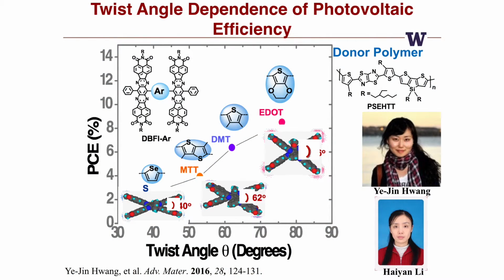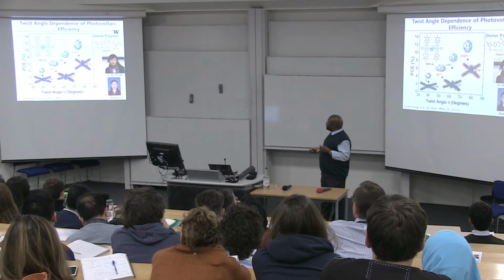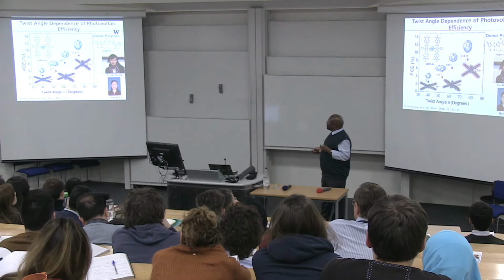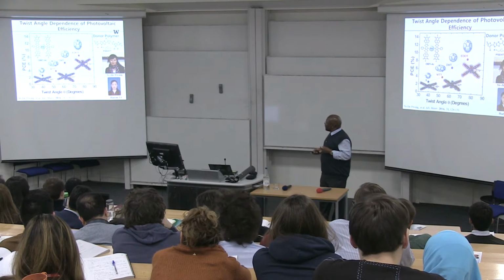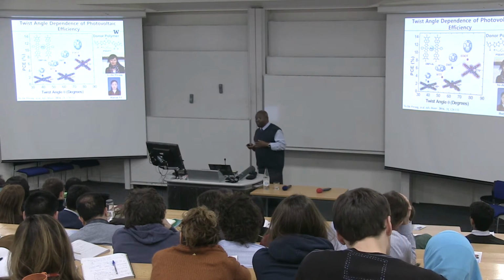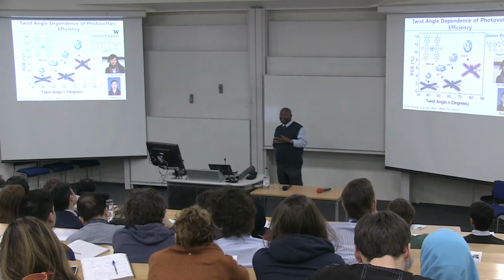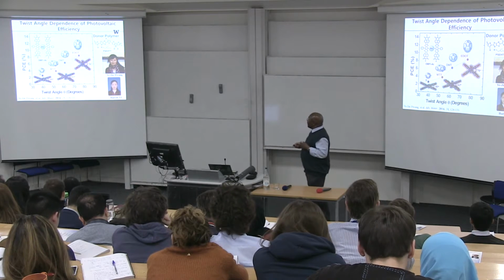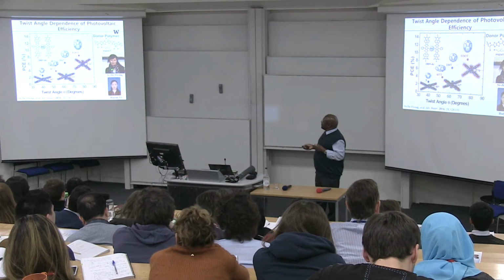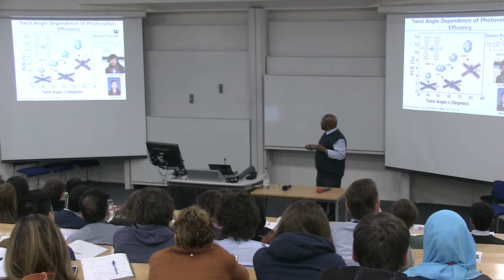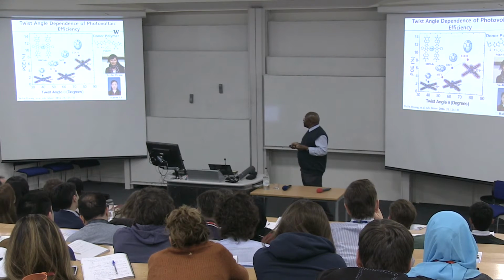So if we plot the efficiency, PCE, as a function of the twist angle, this is purely empirical. We don't have any theoretical basis, but it appears to be linear. And the obvious implication that one can see here is that perhaps if we go to a 90 degree angle, are we going to get close to 11% or so predicted from here? We are currently at work trying to test this idea. Okay, and this is the work of a very talented graduate student, Ye-Jin Hwang, who graduated last year, now a postdoc at MIT.